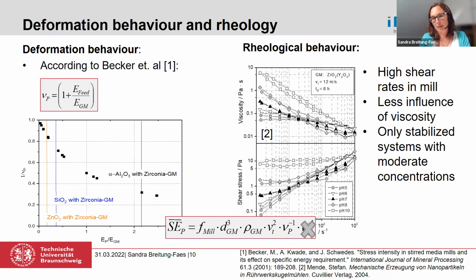If you grind it with a pH value of 5, you have a very stable suspension. So when you look at the suspension in a bottle, it looks like a milky fluid. It's like water, very thin flowing. So the viscosity is very low. If you go up with the pH value to 10, you destabilize your suspension. So the particles start to agglomerate, and with this agglomeration, usually the viscosity rises. And this can exactly be seen here. So the viscosity increases, but only for small shear rates. If you looked at the suspension in a bottle, it would look like a pudding.